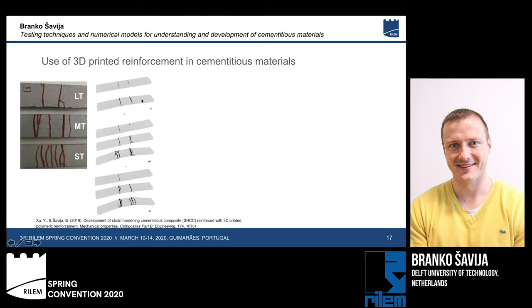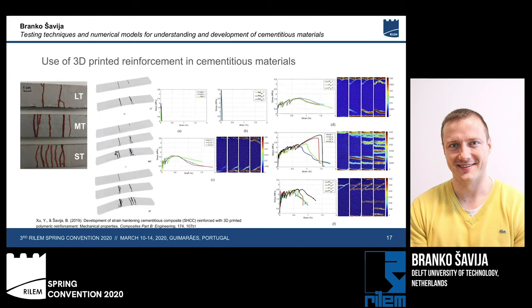Now, also in terms of experiments, we have performed digital image correlation experiments on uniaxial tension specimens. So we see here in figures A and B, reference specimens without reinforcement that collapse in a brittle way. With large triangles, we have some ductility, but it's mainly provided by the pullout of the reinforcement from the matrix. And if we introduce smaller triangles in these figures, we get multiple cracking and strain hardening behavior of our material. So this means, again, that we can use this technology, but we need to optimize it in order to get the performance of the material that we want.